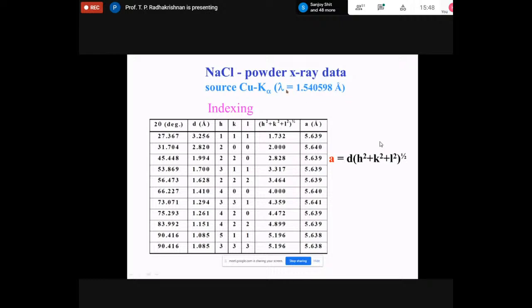Now, using the wavelength of the X-ray, which is known to us because we are running the experiment, you can easily calculate the Miller plane distances, using the equation 2d sin theta equals n lambda. N, by the way, we take as 1, because even if you take 2, 3, 4, and so on, it will correspond to some Miller plane with a higher index. So in practice, we always take n equal to 1. N equal to 3 corresponds to another Miller plane with 1/3 the distance of, say, a 100 plane, for example. So it is built into it. So forget about n for the time being. So 2d sin theta is equal to lambda. Lambda is known and theta is known, so you can actually calculate d.